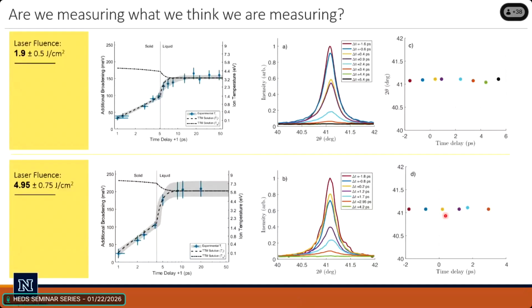So the expansion of the target after we hit it is a very important question. We see no evidence of expansion at all in the solid phase. And why can I say that? Because if we look at the Bragg peak location versus time, which of course is related to the lattice spacing, the Bragg peaks do not shift in any way. So we see no appreciable expansion of the solid up until the melt point. And this is kind of odd to us, but it is what we saw.